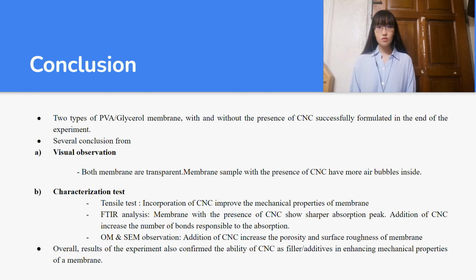While from the results of the characterization test, there are also a few conclusions that can be made. First, the incorporation of CNC in the PVA glycerol membrane improves the membrane mechanical properties. Further, by comparing FTIR analysis results of both samples, the membrane with the addition of CNC shows a sharper absorption peak, indicating the addition of CNC improved the number of bonds responsible for the absorption.